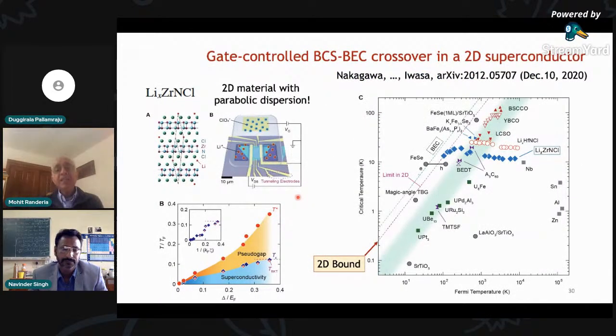But then, rather remarkably, December 10, 2020, appears this paper on the archive. This is from the Iwasa group. The details of the experiment are rather complicated because it's a rather complicated layered material, zirconium nitride chloride, which they put lithium intercalation in. So there's a band insulator in which they are able to change the doping levels of lithium, which donates an electron to this 2D superconductor, and change the electron density by 2 orders of magnitude.